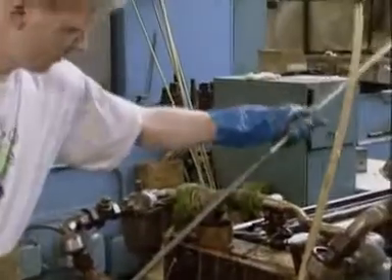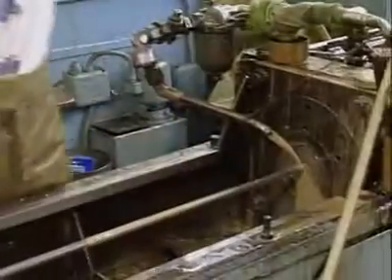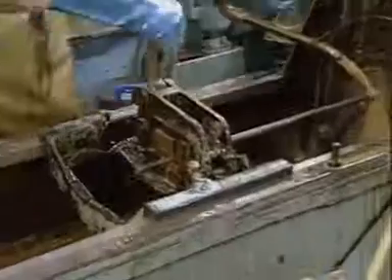Chain drawing quickly and easily adjusts pipe dimensions, but for more critical tolerances, a mandrel is inserted into the tube, which keeps it a constant width and diameter. Hydraulic oil is used for lubrication and cooling. This pipe will be the slider on a trombone.